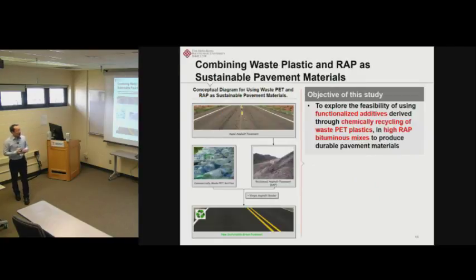So in this study, we were thinking about whether we can first chemically treat the waste plastic and convert it into some modifier or additive, and then use this modifier or additive to improve the performance of the RAP mixture, especially mixtures containing a high percentage of RAP. Our specific objective is to explore the feasibility of using functionalized additives from the chemical recycling of waste PET plastics in high RAP bituminous mixture. And we want the bituminous mixture to be more durable compared with those without the additive.